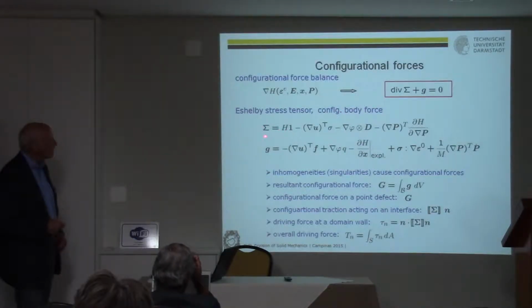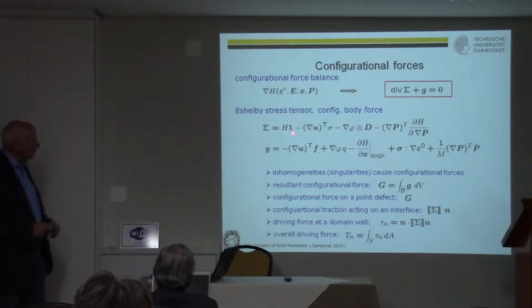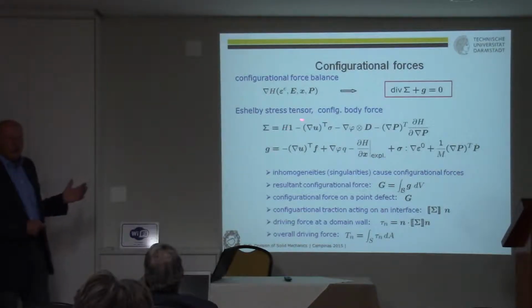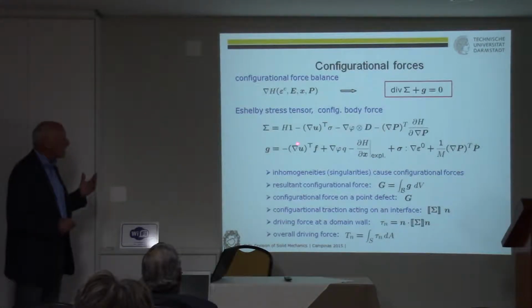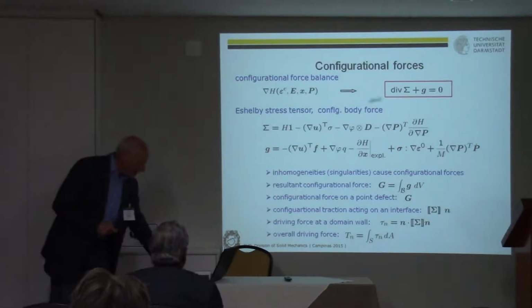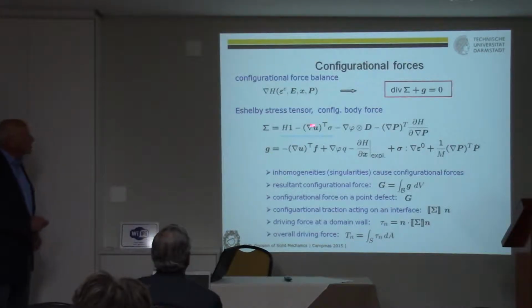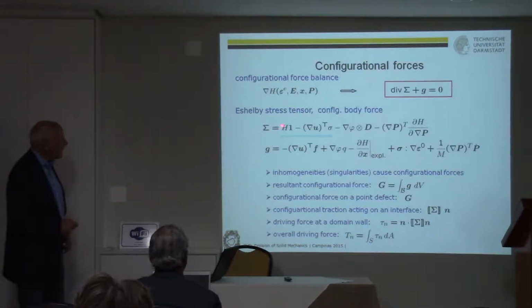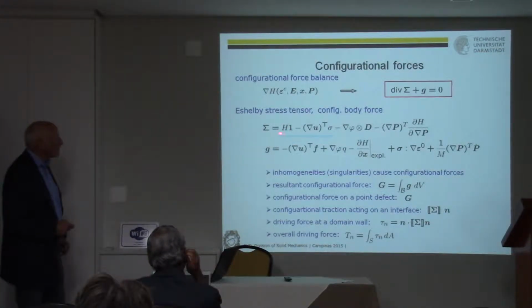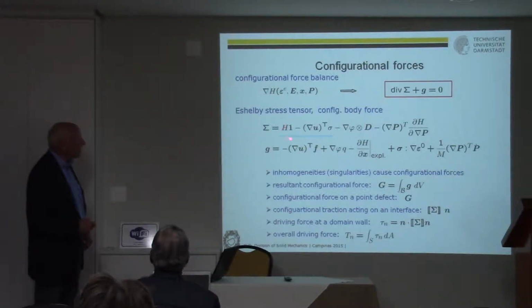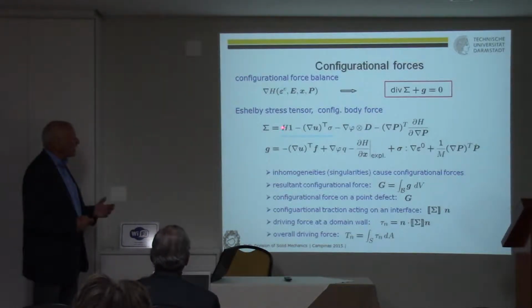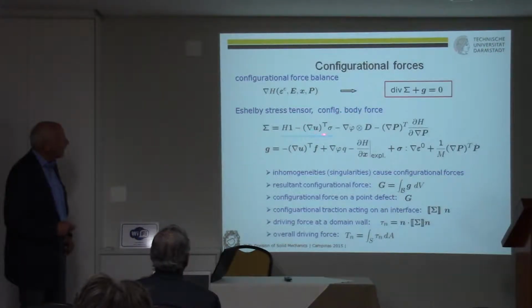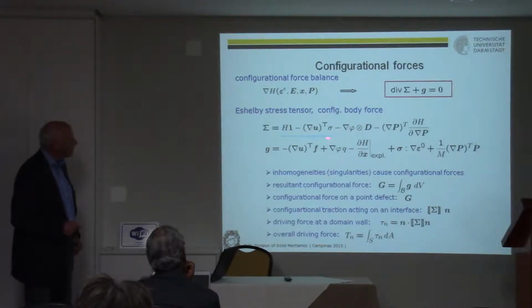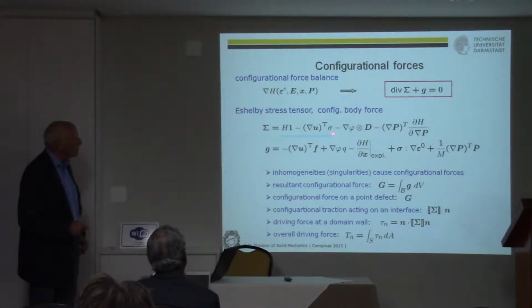But here appears the so-called Eshelby stress tensor. You should not mix Eshelby stress with Cauchy stress or something like this. This is not the pure mechanical stress. Originally, only this part appeared when Eshelby for the first time derived this tensor. What you see here, H, we have explained before. This is the extended electric enthalpy, and if you work in pure mechanics, then it's nothing else than the strain energy. And here the gradient of the displacement and Cauchy stress appear, and these extra terms come from the electric field and the coupling with the electric field.